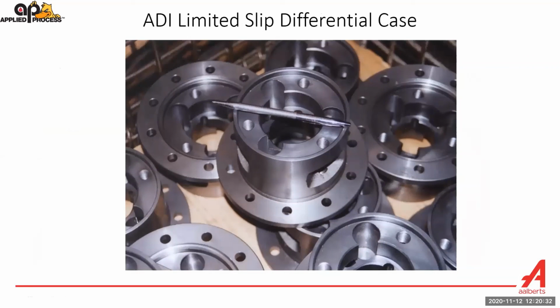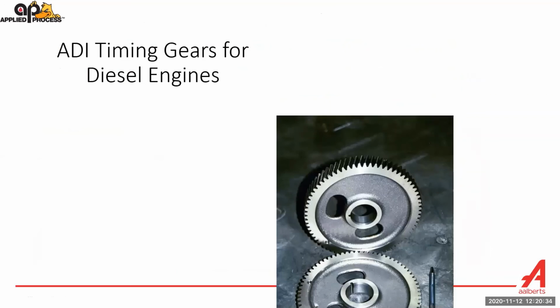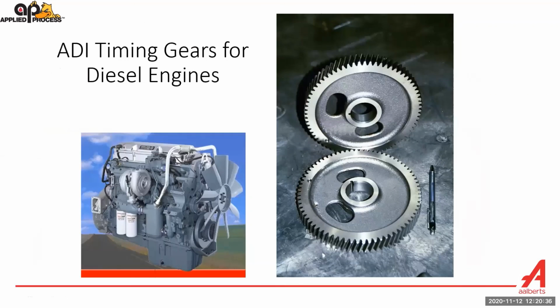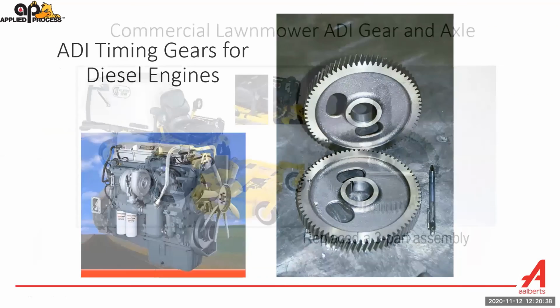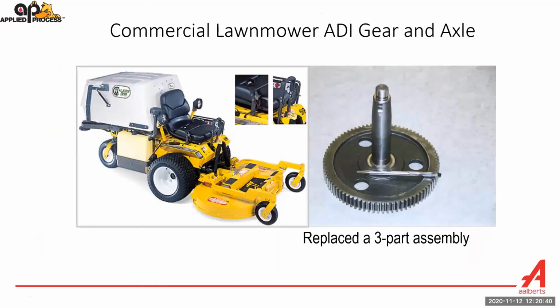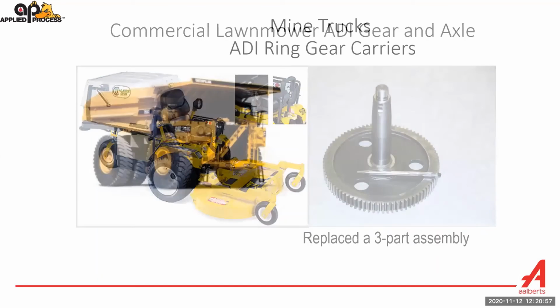Limited slip diff cases, timing gears for diesel engines. This is a 3-piece fabrication that was converted to a 1-piece ductile iron casting that then gets Aust-tempered, and it comes to us pre-machined. So it's complete. That's a testament to the stability of the Aust-tempering process.